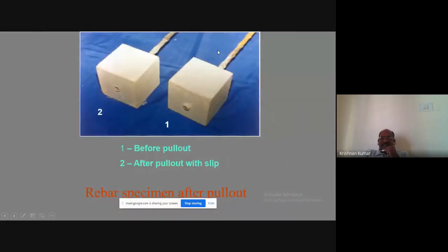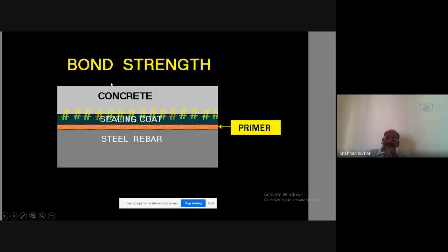And when we are talking about the bond, we have made different bond systems. So this is the bond. We have to have a free end slip. So this is slipped. Then we have calculated the bond between the coated rod and the concrete. Other barrier systems we also selected, but CPCC proved higher bond strength than the control specimen. You see how the bond mechanism is happening here.